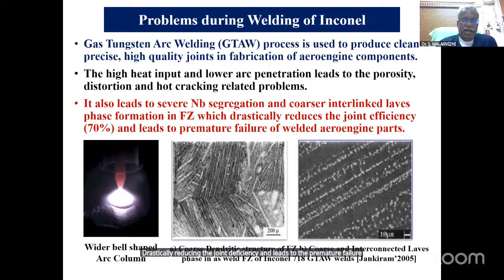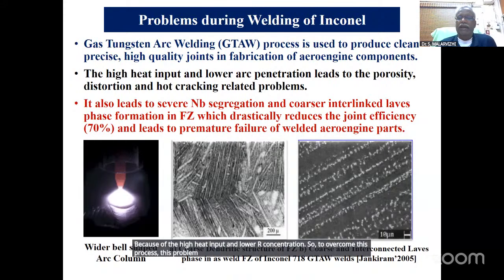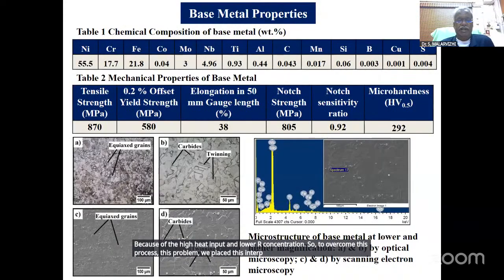So this is the coarse dendritic structure that forms in the welded fusion zone, and here it is a coarse and interconnected Laves phase. The Laves phase is an intermetallic phase. It's a brittle phase which forms in the fusion zone during welding using this GTAW, the conventional TIG welding process, because of the high heat input and lower arc penetration. To overcome this problem, we utilized interpulse TIG welding, constricted arc welding.